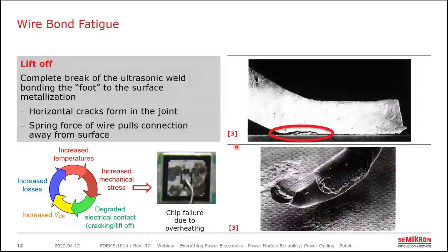So similarly, we can have cracks that form horizontally in the bond wire foot, where spring force eventually pulls the bond foot right off in what's called liftoff. And part of what determines whether the failure is a heel crack or a liftoff is the shape of the bond wire loop, which is called the aspect ratio. But the development of this failure mode and the end result is the same.